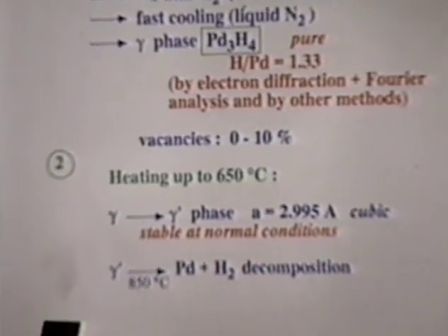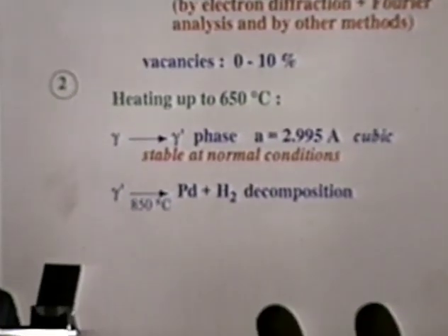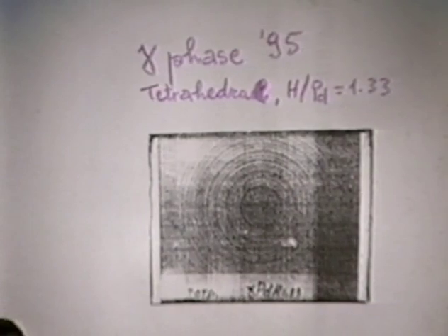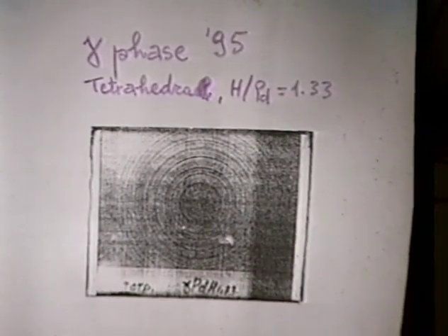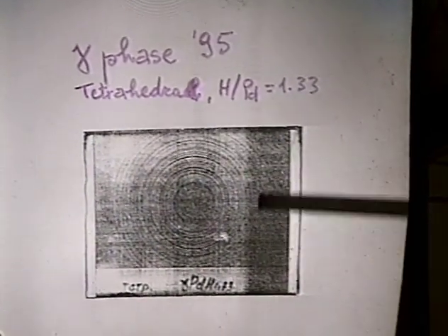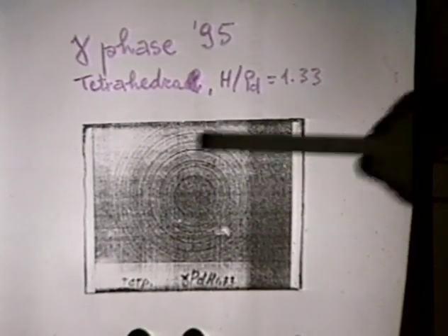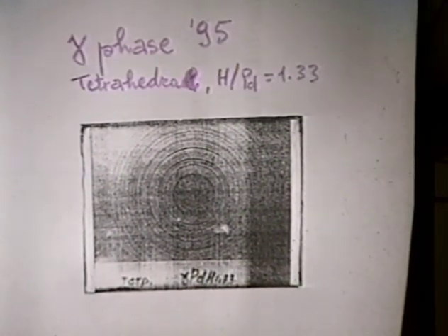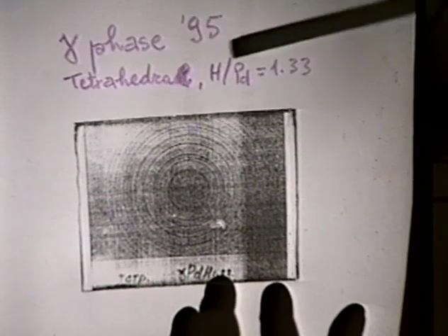By electron diffraction, we know this, and also by Fourier analysis and by other methods. The diffraction gives you a very nice, pure pattern. This is a bad transparency, but the original one is much cleaner, which shows clean tetrahedral rings corresponding to the tetrahedral structure and pure 1.33 ratio, which is measured also in other ways.